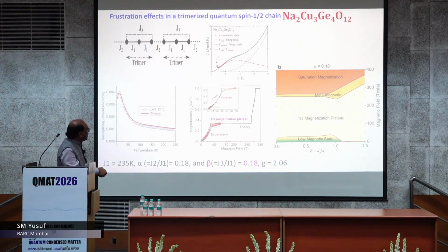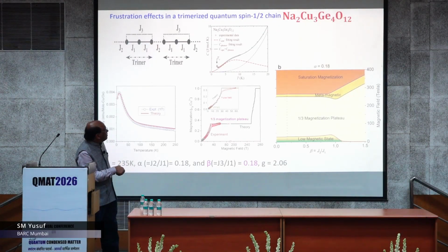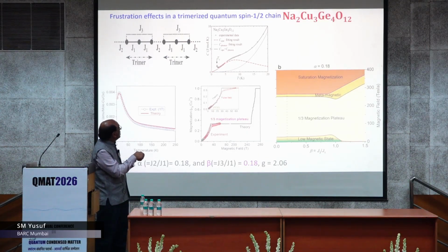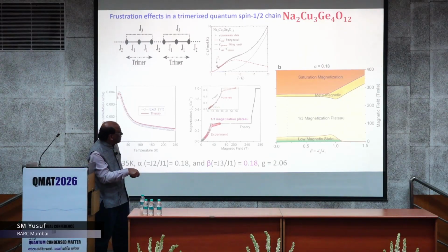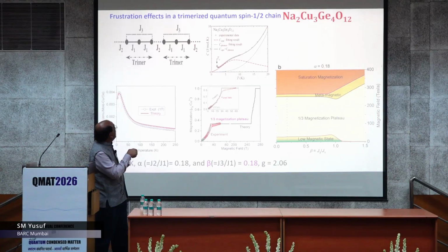And in this system, you see the magnetization, a quantum 1/3 magnetization plateau, experimentally and theoretically supported. Specifically it is also shown here. What is important to note here is that J3 by J1, that is, when these end spins interact, it gives the frustration, and beyond a certain strength, the so-called low magnetic field state disappears. So this is the effect of frustration in this quantum entangled spin system showing a 1/3 magnetization plateau.